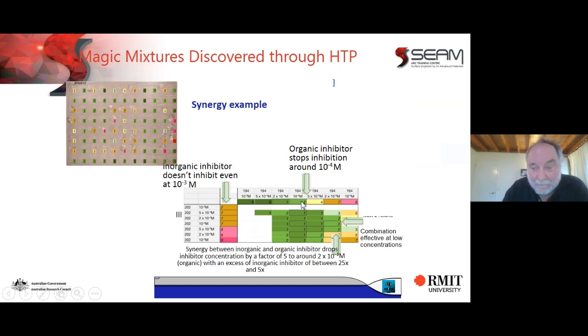So by itself, the organic inhibitor is effective to about 10 to the minus 4 molar in concentration. And the inorganic is not really effective at all. But combined, we can get the combination to be effective when the organic is 2 by 10 to the minus 5 molar, and the inorganic is 5 by 10 to the minus 4 molar.